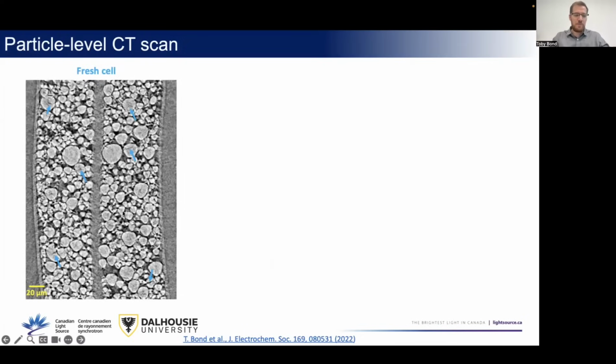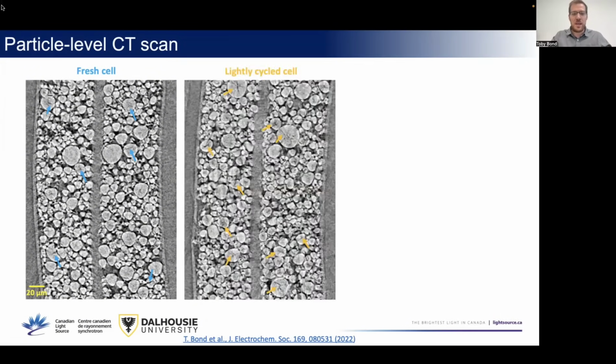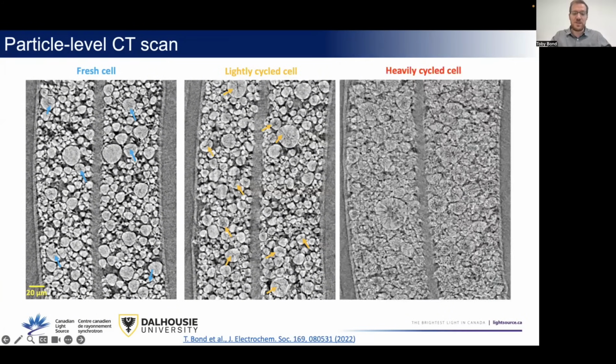So if we look at the fresh cell and go straight down to this particle level CT scan, you can see that the particles look very healthy. They're nice and dense. There are some little cracks where these blue arrows are pointing, and that's probably from the manufacturing process, where a lot of pressure is applied to them during the coating process. So you get some cracks initially, even in a fresh cell. If you compare that to the lightly cycled cell, you'll start to see some little cracks pop up here and there. I'd say there's more cracking going on here than in the fresh cell. But if you look at the heavily cycled cell, it's a very different story indeed.